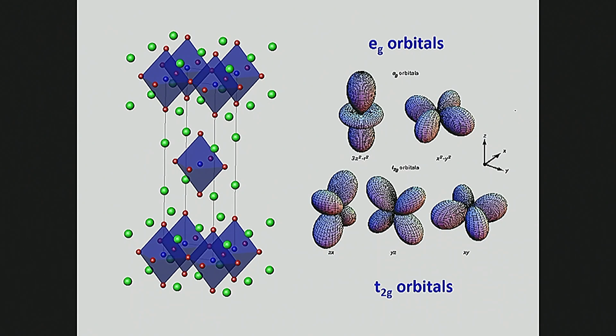So for transition metals, it's often the case that their magnetism is particularly simple. And that's because an architectural motif that's very common in transition metals is this motif here, which I don't know how well you can see. Basically, there's a transition metal ion, like copper or manganese, in the middle of this oxygen-6 octahedron. If this was an insulating state, the oxygens would be in a 2- oxidation state, since oxygens are very electronegative. The copper or the manganese would be in something like a 2+ oxidation state.